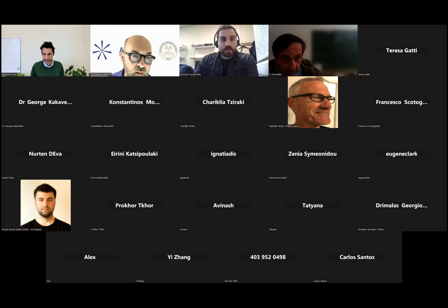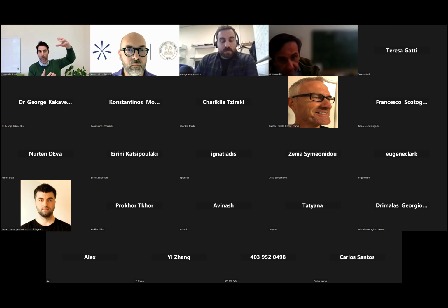Yeah. So the temperature has a direct effect on the modulation depth. I have to say that I didn't want to go too much into the details, but now we know that it's not only the temperature, but there is also Pauli blocking that plays a role. I would say that rather than changing material, which is of course possible, what one can do is change the conditions around graphene. I say that because if you would do the same in a TMD, you have a band gap. So even if you have a very large electronic distribution, at some point the Fermi distribution would fall into the gap, and then you are limited in the amount of changes that you can do, no?